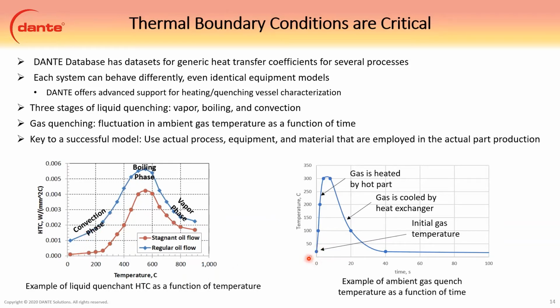For gas quenching, you have to consider the ambient gas surrounding the part. So this shows if you took a part out of a hot furnace and stuck it into a cold gas chamber, this is the temperature of the gas around the part that essentially drives the heat transfer. So you can see as the part enters the chamber, it gets heated up. And then as the gas is cooled by the heat exchanger, the gas around the part eventually drops back down to the ambient. So all of these have to be considered.